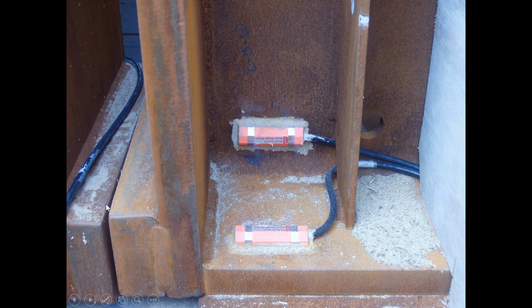Now remember also there's going to be concrete surrounding that, so that concrete is going to be confined. And so you won't have as much problem in that. That's why an inch or so is fine. You're not going to get into a problem. We don't recommend just having an end plate with a complete gap because that will create a problem, because the axial stiffness of the system at this point is much higher than here. So okay, you can't get by just with an end plate. You have to have these steel blocks, but if you have about a 1 inch gap, you should be fine.